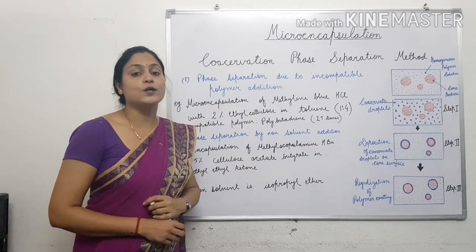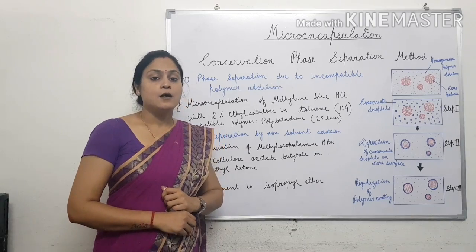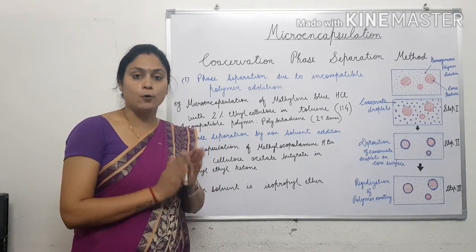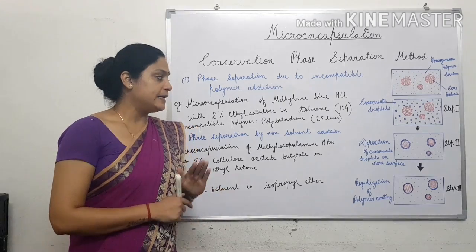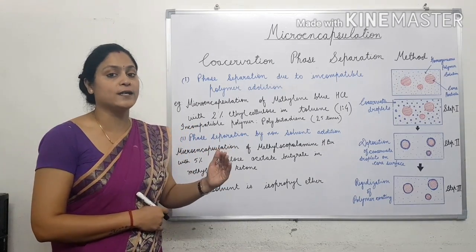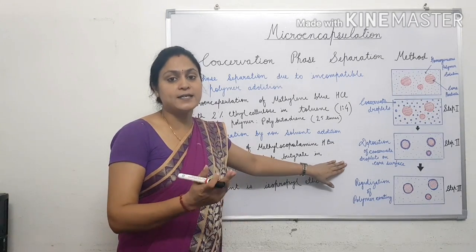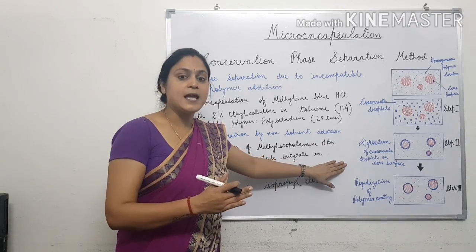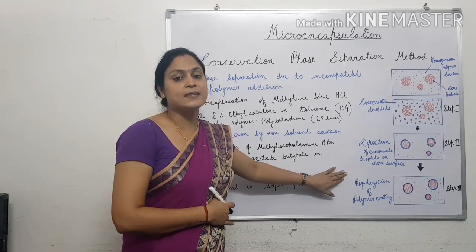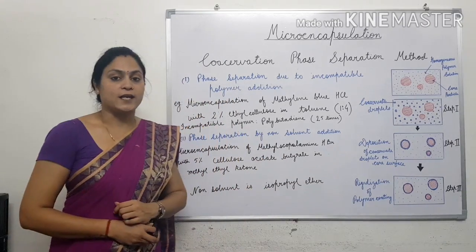Polybutadiene, which was added as an incompatible polymer in the ratio 1:25, that is 25 times the coating polymer, is more soluble in hexane as compared to toluene. So most of the extra polybutadiene dissolves in hexane and separates out, and this also results in the rigidization of the ethyl cellulose coating.